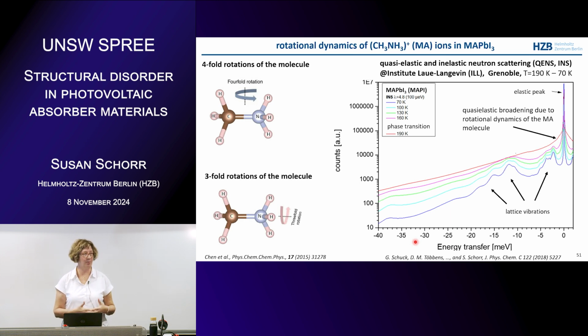The rotational dynamics. What are the rotational dynamics? So this is the molecule, for instance methylammonium, and it can rotate around this axis, so it can rotate like that. Or there is a 3-fold rotation along the CN axis like that. So this is a measurement that we obtained at the Institut Laue-Langevin in Grenoble at the reactor source there. And this is called quasi-elastic or inelastic neutron scattering. Now here you see an energy scale. This is the scale which measures how much energy the neutron has transferred to the sample during the measurement.